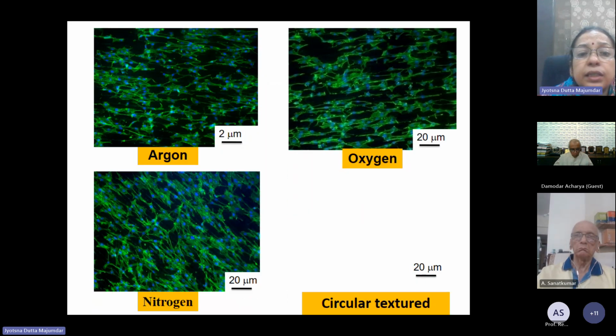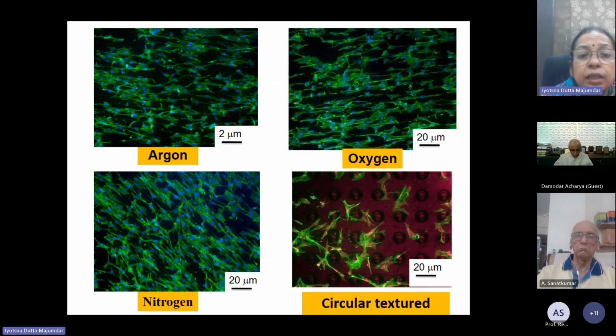When we did texturing, we found that nitrogen textured samples offered maximum adhesion of the cells, and cell attachment was parallel to the textured surface. Wherever there was texturing, adhesion was maximum. In the circular texture sample, we found that inside the circle or groove, there was not much attachment of the cells.